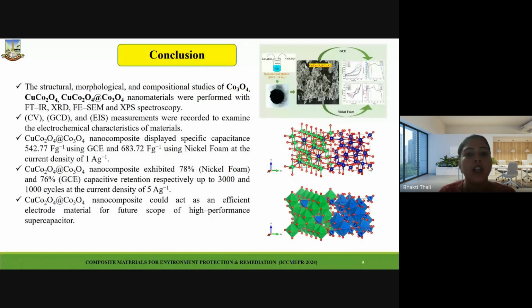Lastly, the conclusion: all the materials which we have synthesized are successfully confirmed with techniques like FTIR, XRD, SEM, and XPS spectroscopy. Electrochemical measurements were also done to understand the electrochemical performance of the materials. On glassy carbon, the composite delivered 542.77 Farad per gram, and on nickel foam, it delivered 683.72 Farad per gram at a current density of 1 ampere per gram.